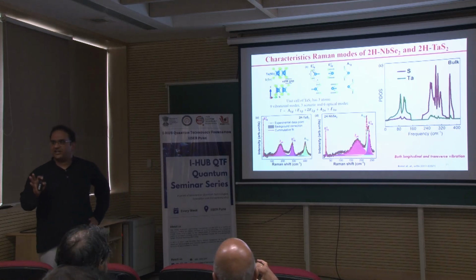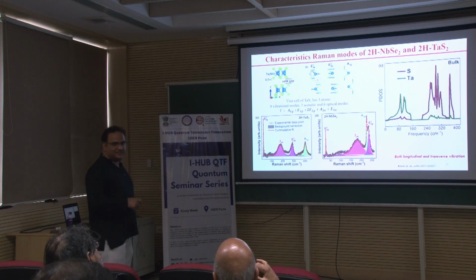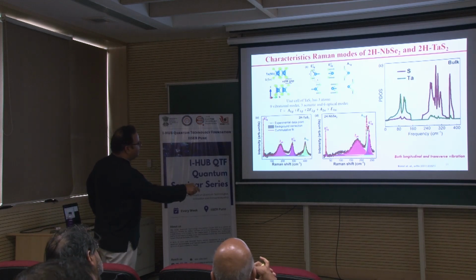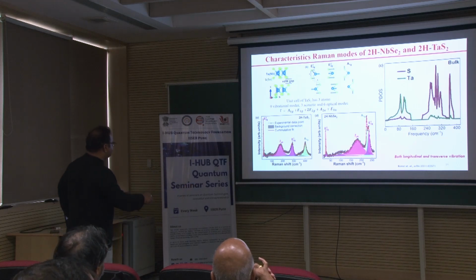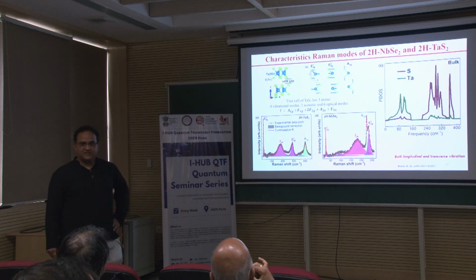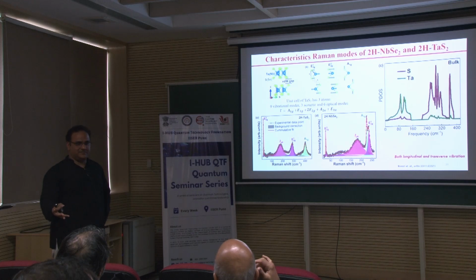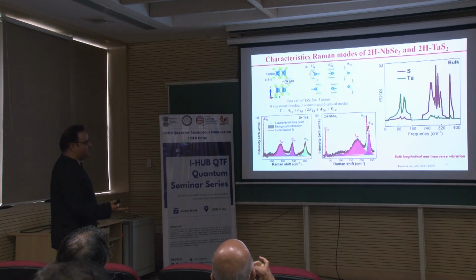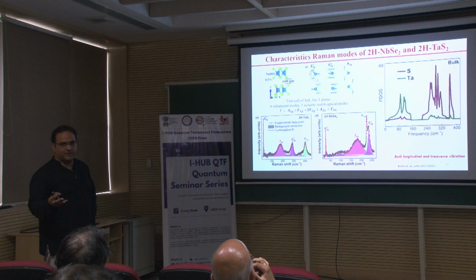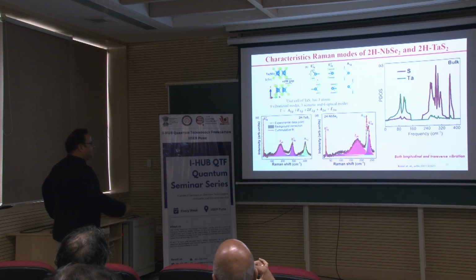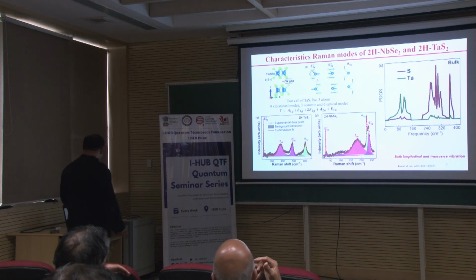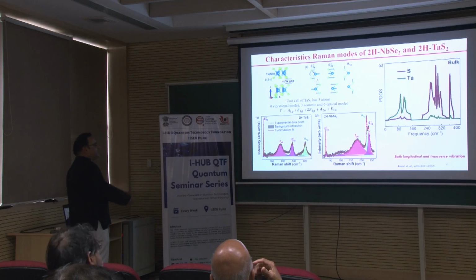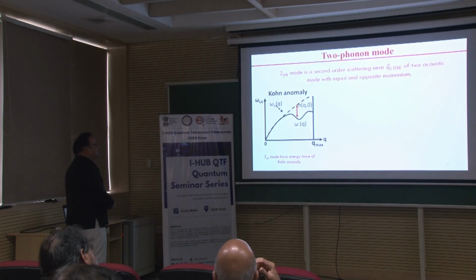So you do not expect anything in that region, but this is the region of 140 to around 180 for tantalum sulfide, 140 to around 180 or 200. That is where the 2-phonon mode is coming. From where is that mode coming? What is the origin of this mode, and above all, what is the symmetry of this mode? Theory does not say there is a mode. This is there in niobium selenide as well, but I have not shown it here.